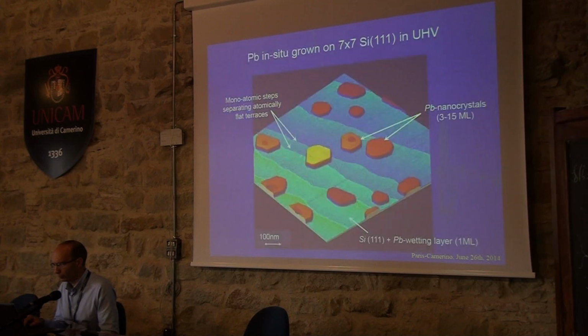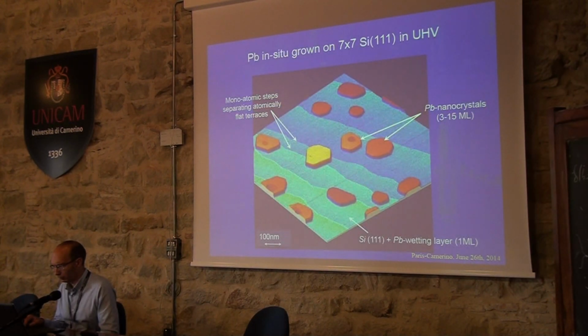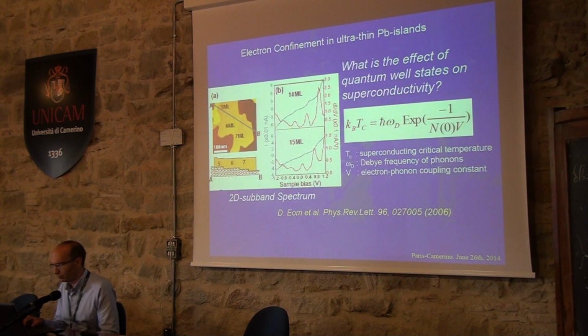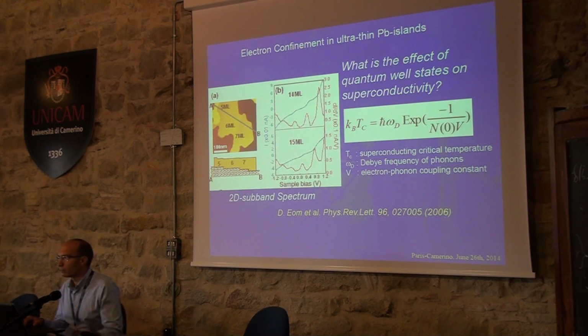So, these are these islands, and it was believed that depending on the thickness of the islands, you will get different superconductivity. Since depending on thickness you have a quantum well confinement effect in these islands, at some thicknesses you will get enhanced superconductivity because the Fermi level will lie in this confinement-induced electronic structure.